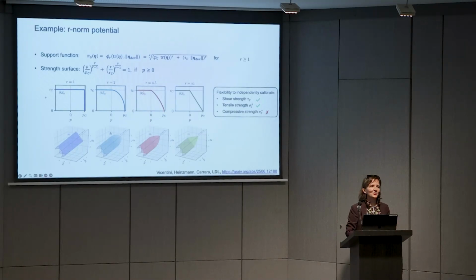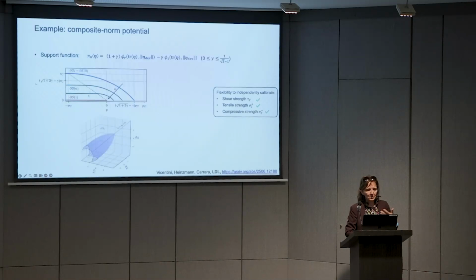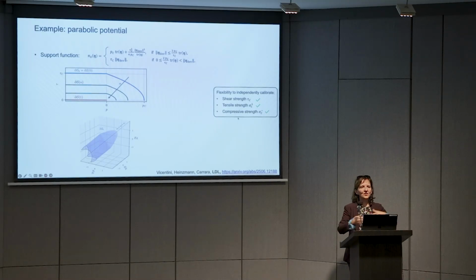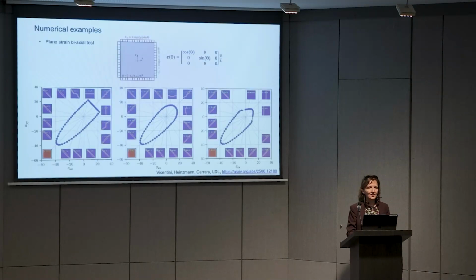And finally, we can have strength surfaces of arbitrary shape, which we can calibrate. So for instance, this is one choice which gives you a strength surface of this type, and you can calibrate. In this case, you can only calibrate the tensile strength and the shear strength, and the compressive strength will follow automatically, but then you add one more term with one more parameter, and then you can calibrate independently all three properties. So essentially here now finally we have a very ample margin for maneuver, so we can really calibrate any convex strength surface, quantitatively and qualitatively.